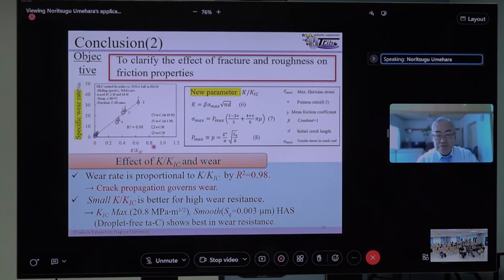The friction property can give the change of sigma max, and a is the initial crack length, which comes from the surface roughness. Sigma max comes from the friction coefficient. If we can evaluate the stress intensity factor from the friction property, we can get a very good result like that. And here my talk ends.